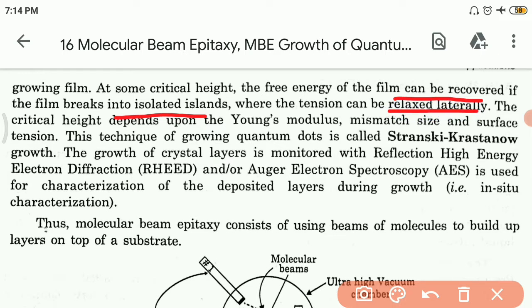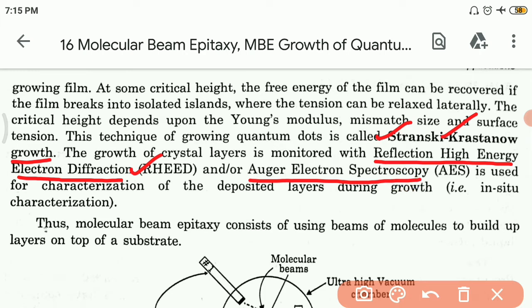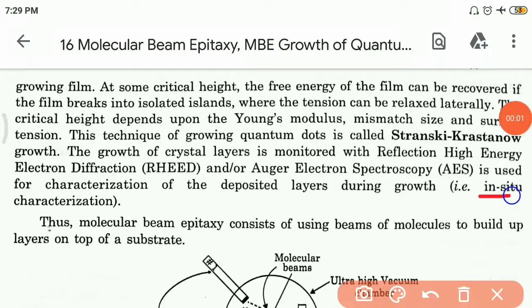Okay, so the critical height here depends upon the Young's modulus, which is the elastic constant, the mismatch size and surface tension. So this technique of growing quantum dots is called Stranski-Krastanov growth. Here the growth of crystal layers is monitored with reflection high energy electron diffraction, that is in short RHEED, and or Auger electron spectroscopy, that is AES, which is used for the characterization of the deposited layers during the growth process, that is in situ characterization.